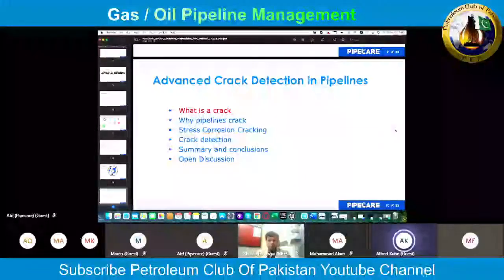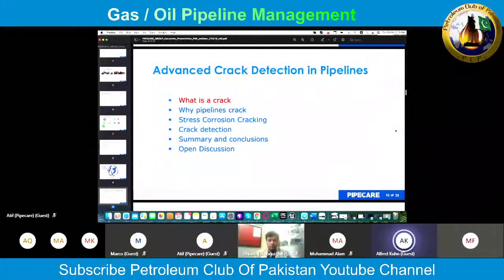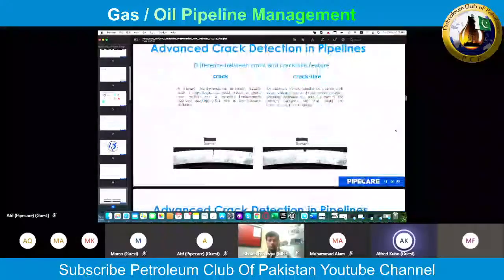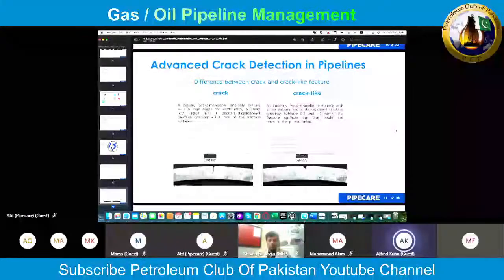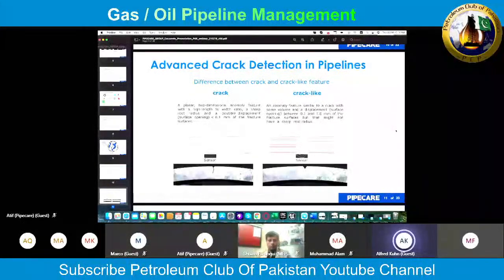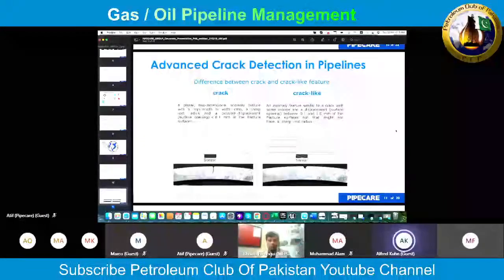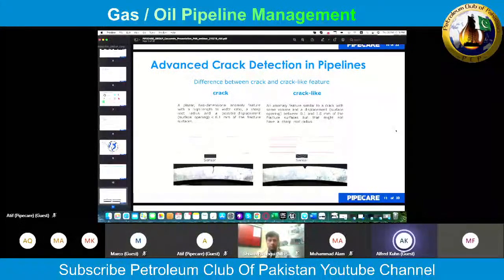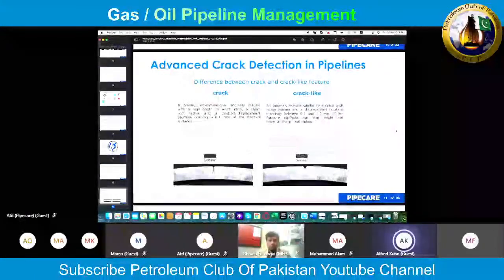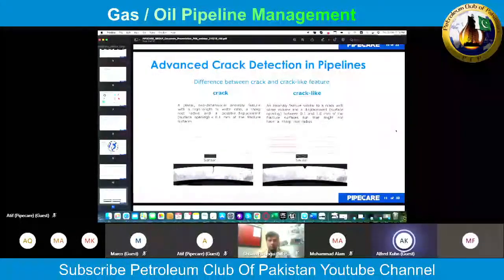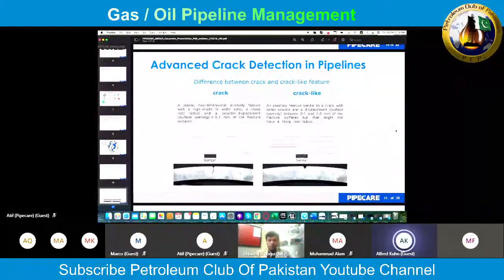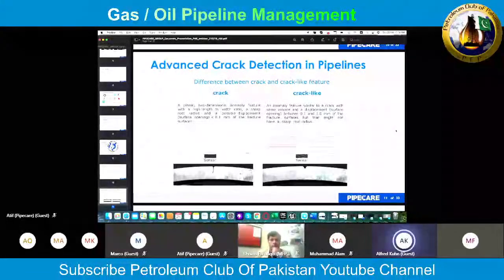So first of all, we need to talk about what a crack is. Next slide. Unfortunately, as we have only a PDF available, you see the full slide, which would normally show up in steps. But independent of that, I'm using the definition from the Pipeline Operators Forum for crack and crack-like feature. A crack is a planar two-dimensional anomaly with a high length-to-width ratio, a sharp root radius, and a possible displacement surface opening smaller than 0.1 millimeter of the fracture surface.